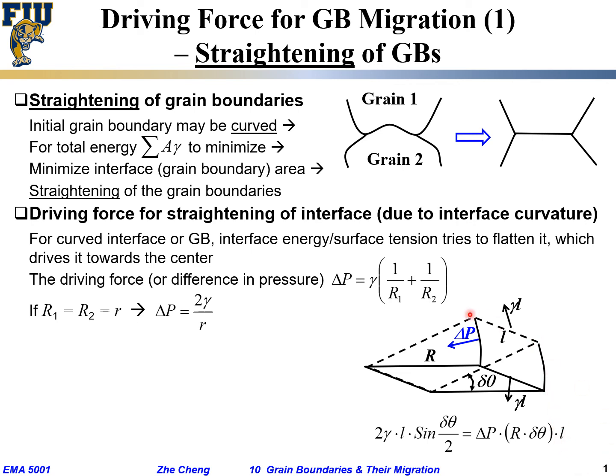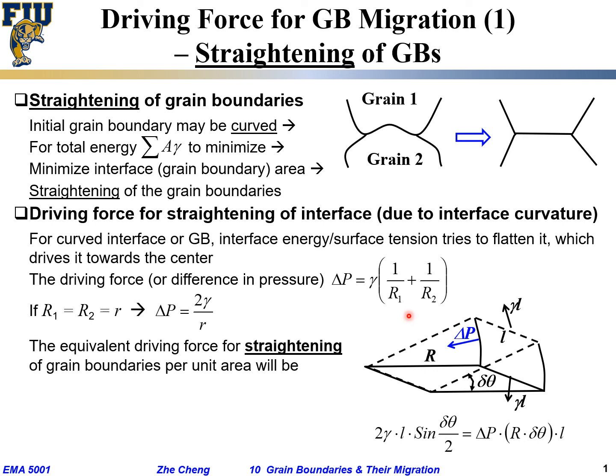R times delta theta gives the arc length from one edge to the other, and times l gives the total area of that small curved surface patch. Area times pressure difference is the net force pointing toward the axis. Setting this equal to the two surface tension forces and doing the simple math, delta theta, sine delta theta, and the two's cancel, giving us the relationship delta P equals gamma over r. Extending to two dimensions — curvature along two directions — gives us the full equation.